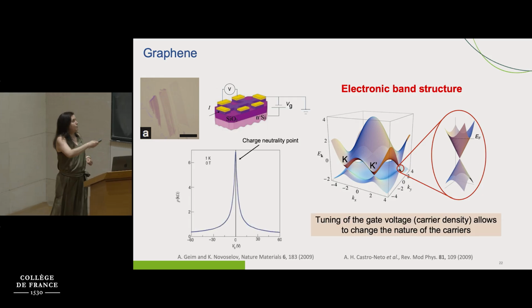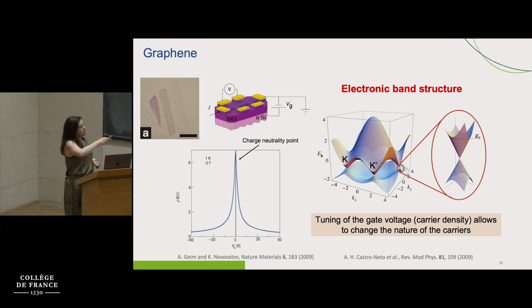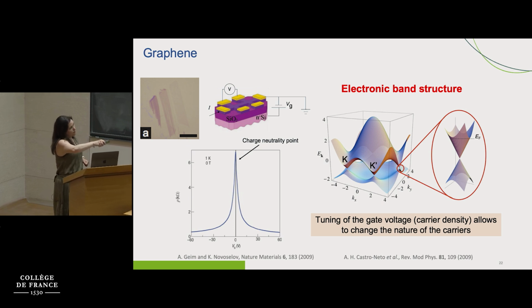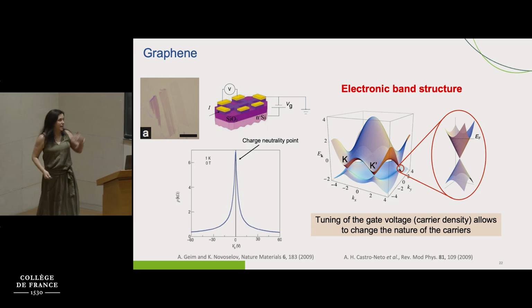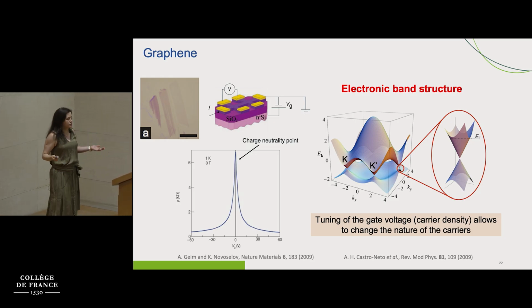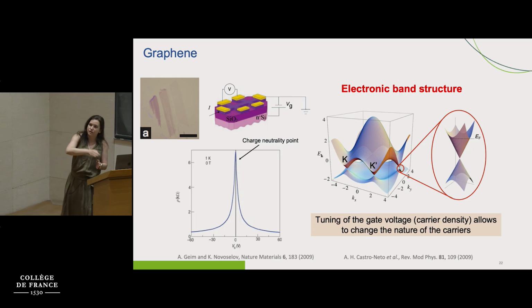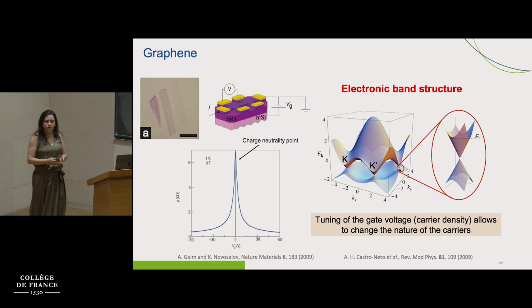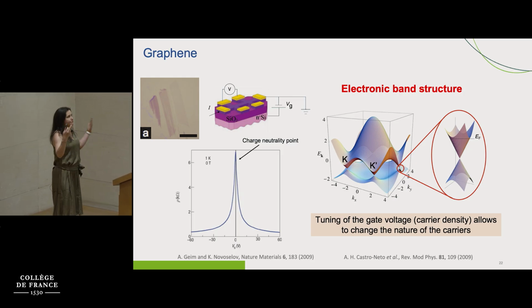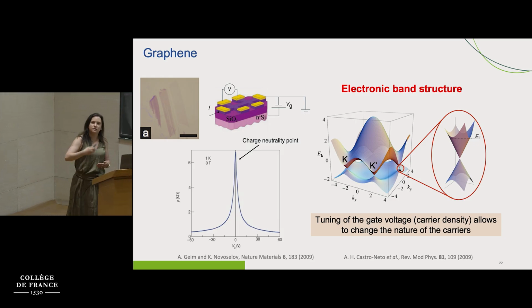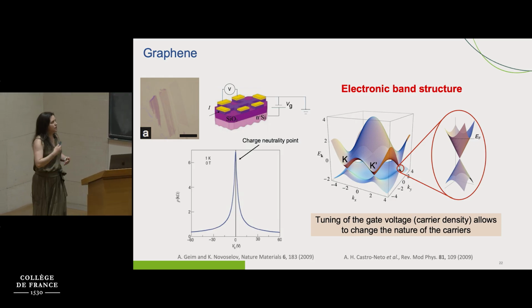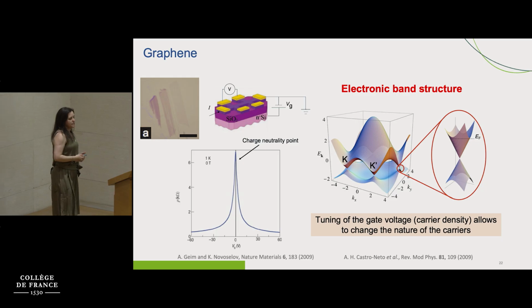And this peak in the resistance is the charge neutrality point, which means the point where the conduction and valence band touch each other. And this is one of the most important characteristics of graphene. We can tune the carriers from electrons to holes. So we have a knob that we didn't have in gallium arsenide. It was not as useful in gallium arsenide because you decrease the mobility of your systems.